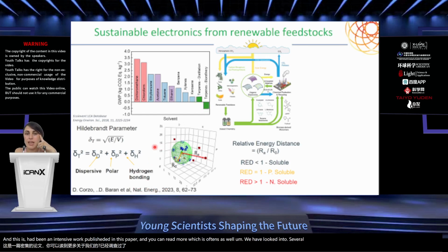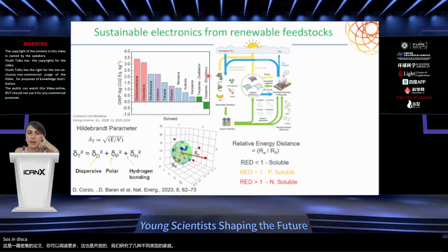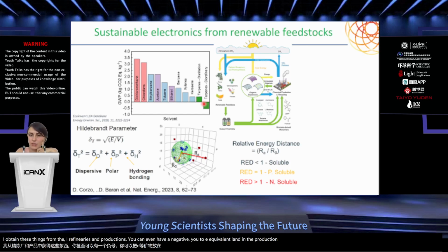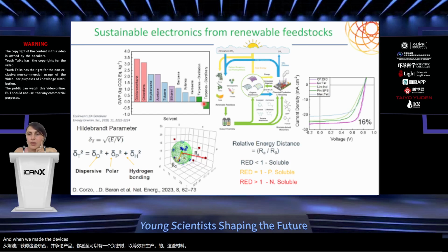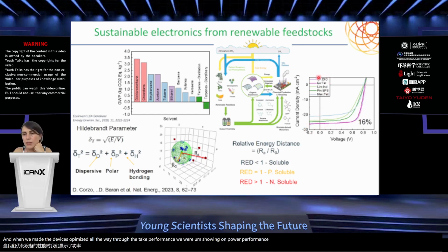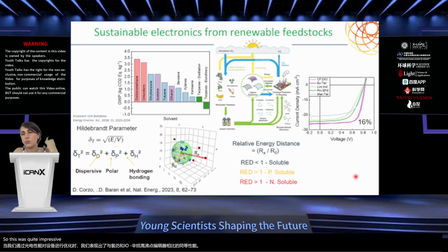We have looked into several different terpene family solvents in this case that are used or produced from distillation, which are quite low in CO2 equivalent, and also modeled that if we can obtain these things from the biorefineries and the algae productions, you can even have a negative CO2 equivalent in the production of these materials. And when we made devices and optimized all the way through the photovoltaic performances, we were showing on-par performances compared to the chloroform and diiodooctane high boiling point additives.